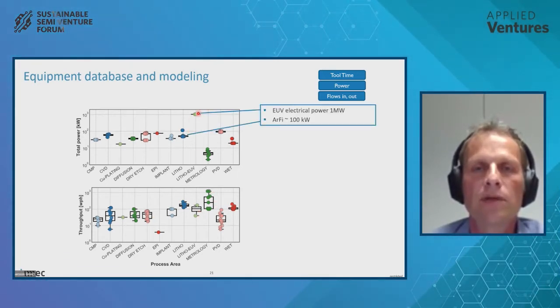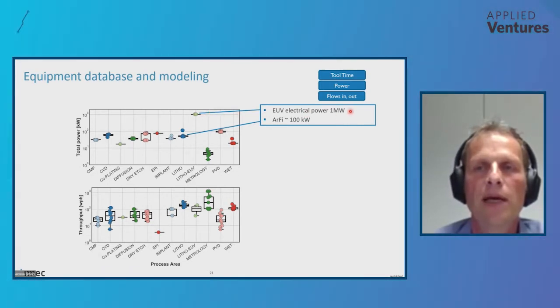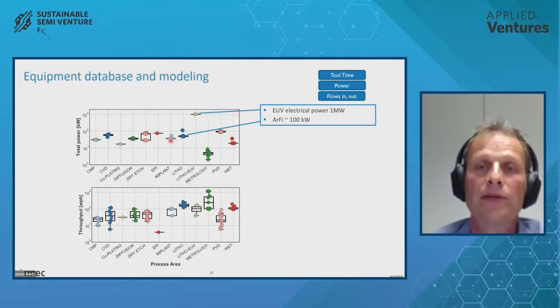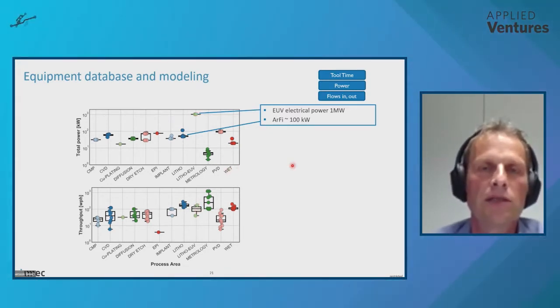One point is standing out, and that's the EUV, which is using quite a lot of electrical power, 1 megawatt, compared to the previous technologies using immersion, which was more like 100 kilowatt per tool. At the same time, the throughput for EUV, at least in the initial stages, was not that great. So that caused an issue, and I will show that actually today it's less of a concern.